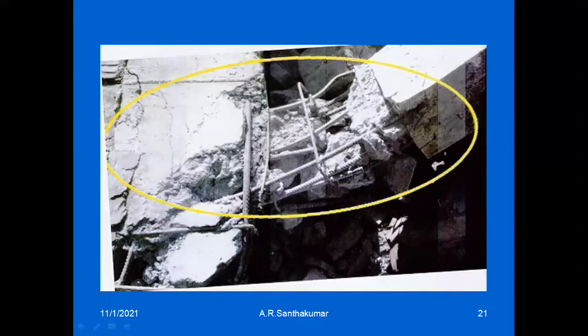Steel did not yield because there was no sufficient development length for the steel. The steel had been pulled out. Because of insufficiency of development length, all the steel had pulled out. Not only that, the required confining steel at the plastic hinge has not been provided. You can see that the stirrups provided are at large distances, not introducing confinement to the concrete.